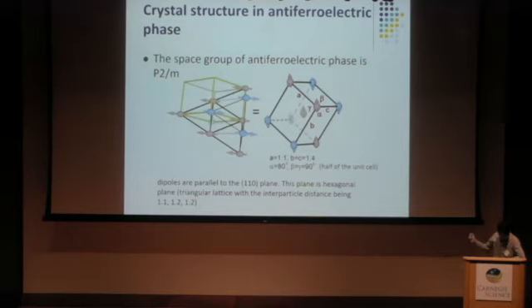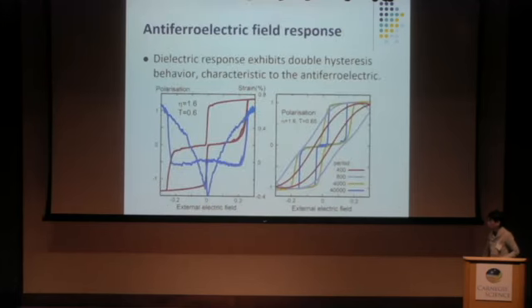So in this phase, the crystalline structure can be examined, and we found this state is monoclinic. To confirm this state is really antiferroelectric, we examined the response to an external field, displayed in the right panel as the red line. The double hysteresis characteristic of the antiferroelectric phase is obtained, because under a strong field, the antiferroelectric phase transforms into the ferroelectric one.